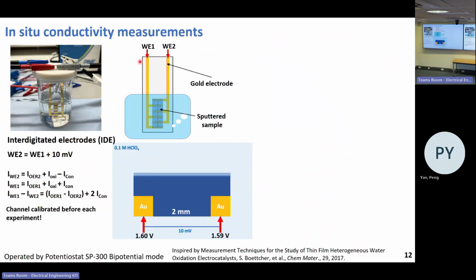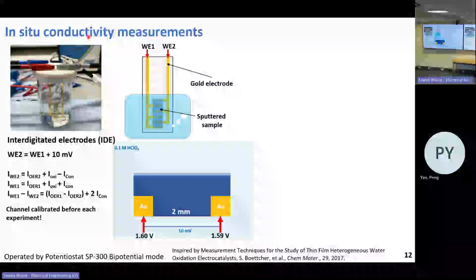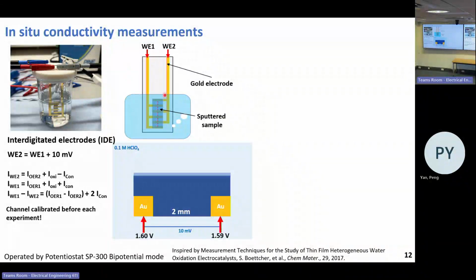So I've developed an interdigitated electrode to look at the conductivity change under water oxidation conditions in situ. We have two working electrodes made of gold, and the samples were sputtered on top of this gold electrode to bridge these gaps.